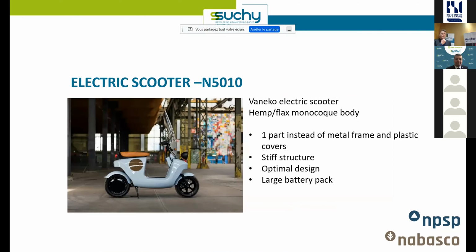So if I come back to the scooter, this is the scooter we studied as a case study within SUCHY, where it's a monocoque structure. We made it out of non-woven hemp because at that time there was only woven flax available as a biocomposite besides that. But we thought about reducing costs by using the non-woven material. We made a monocoque structure, which is very stiff and relatively light. Actually it's a really big battery casing in the shape of a scooter, so we can put in a lot of batteries, and it's a very strong and stiff product. I'm happy to say once we had an accident with the scooter. We crashed into a police car, and the police car had 6,000 euros of damage, but our scooter had only one part damaged, and this was a metal part.